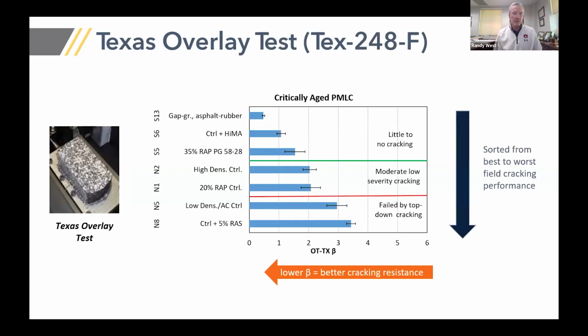One of the other tests that was popular 10 years ago and still is used in research mode is the Texas overlay test. And here you can see very clearly that the test ranked the mixes correctly. Those with the best cracking resistance had little to no cracking in the overlay test. And I should point out that the overlay test beta parameter, some people call this the crack progression rate, CPR, a lower number is better. And the mixes at the bottom of this chart are the mixes that had the highest beta, which means they were least resistant to cracking, and that's exactly what happened with those test sections in the field.